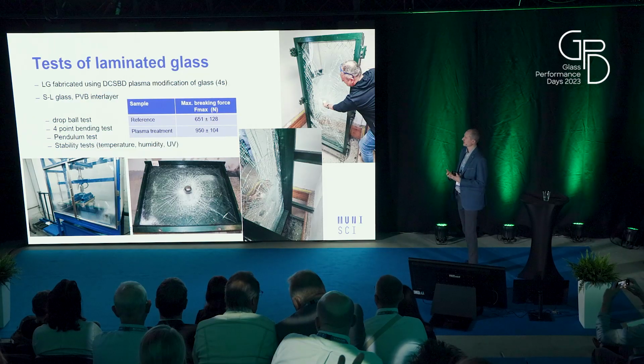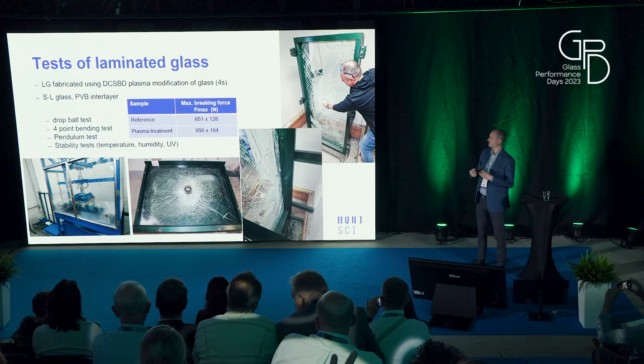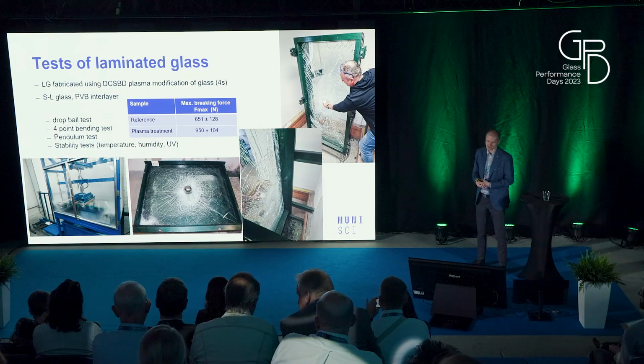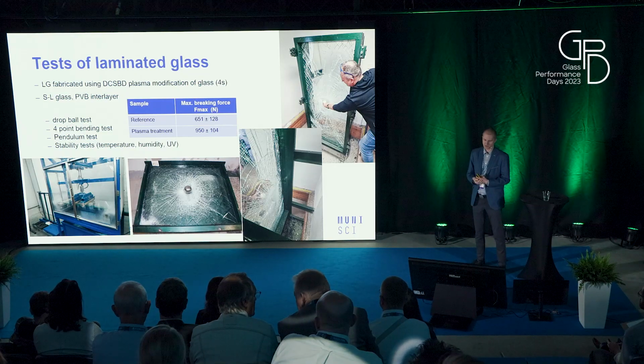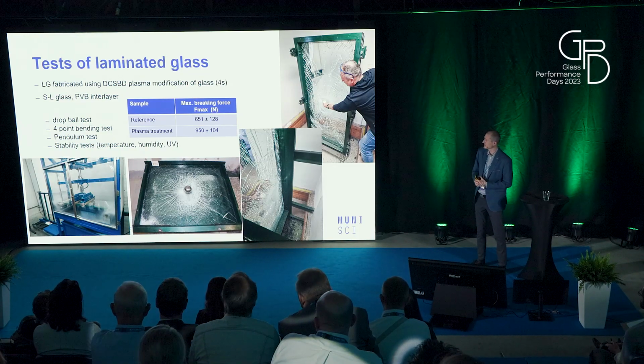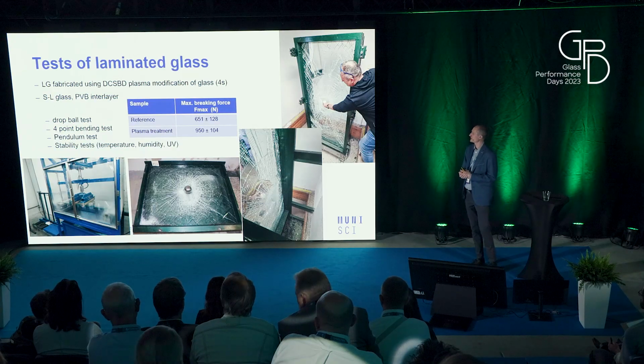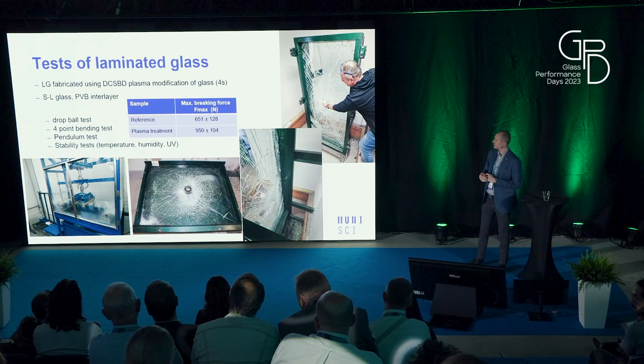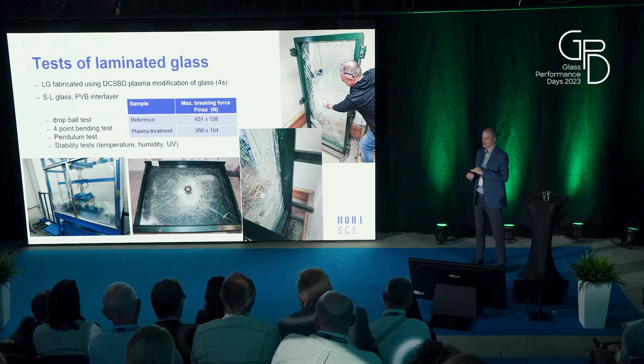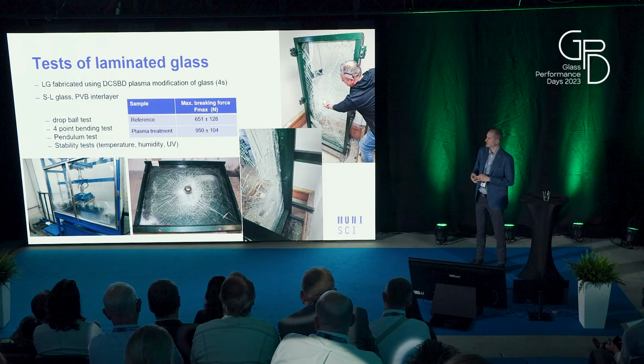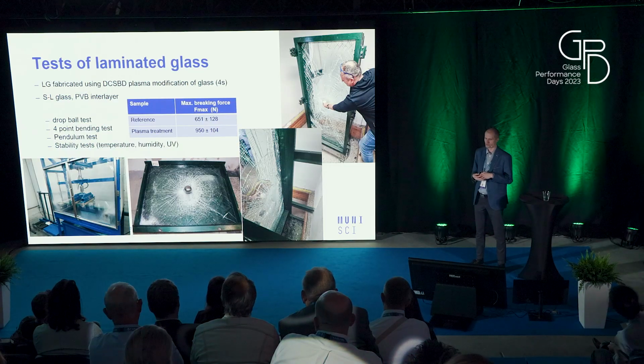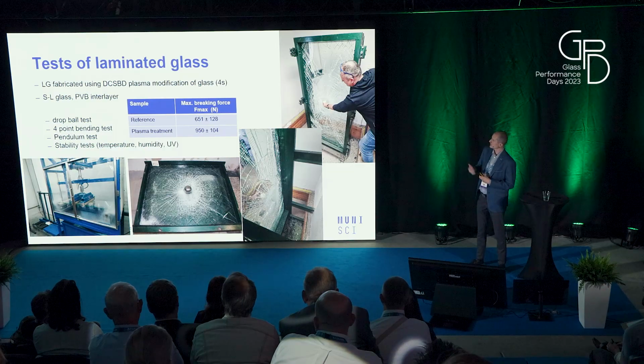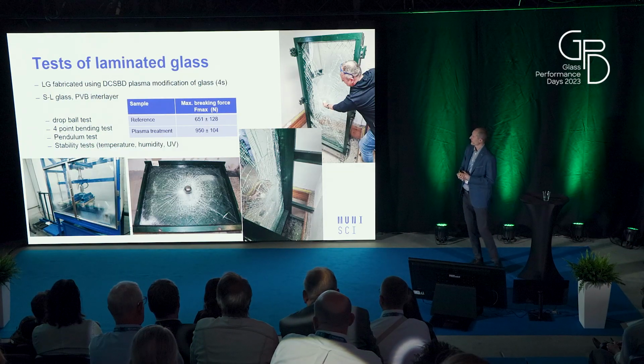We used different types of analysis. We carried out a drop ball test, 4-point bending test, pendulum test, and also some stability tests. All the stability tests we carried out prove that there is no change if we run a temperature stability test, humidity test, or UV radiation test. So let's discuss, for example, the 4-point bending test and pendulum test.